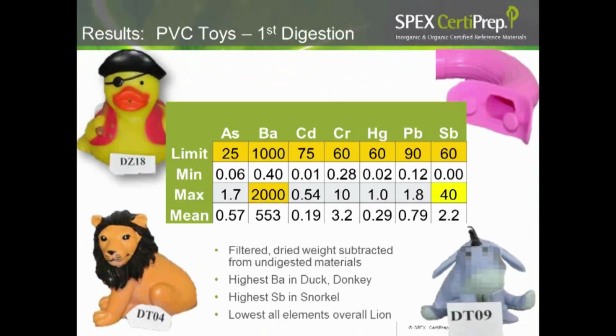Two results that did catch our eye, though, were a large amount of barium, which was found in our duck and our donkey samples, and some antimony, which was found in our snorkel. Now, the antimony we found at 40 milligrams per kilogram is under the limit of 60 milligrams per kilogram, but for a toy that's being placed in the mouth, that's a pretty high result for a toy that is meant to go in a child's mouth and have sustained contact with their mouth.